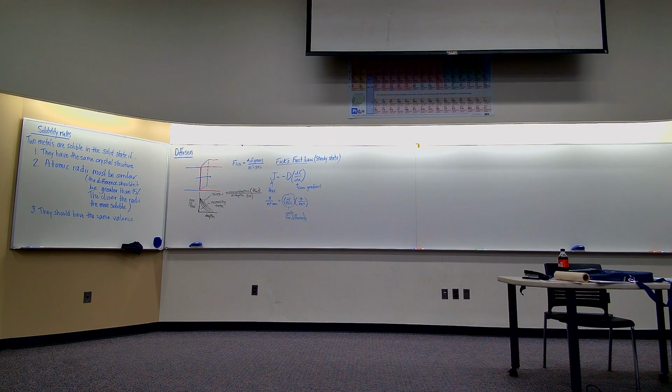For our purposes, when we talk about one element diffusing into a metal, it's usually at the surface because we're trying to harden the surface. And at the surface, it's typically not linear. We'll get into the non-steady state equation in a moment. But that's Fick's first law.